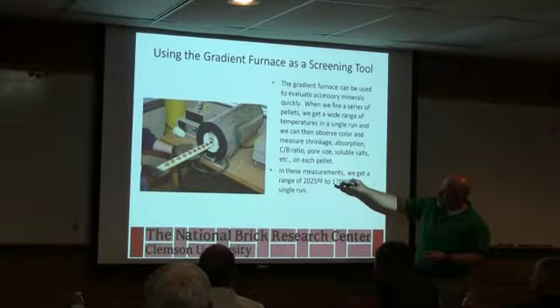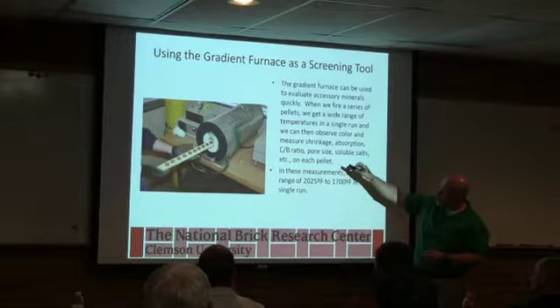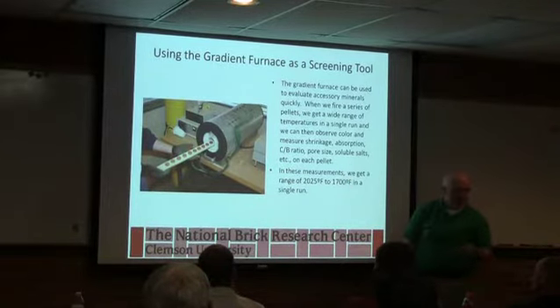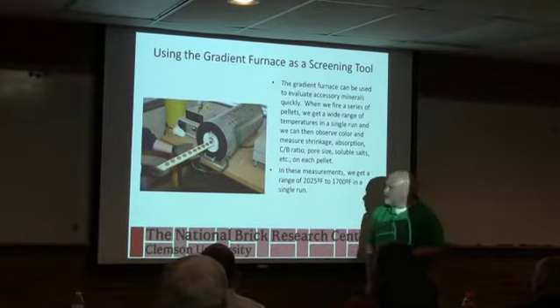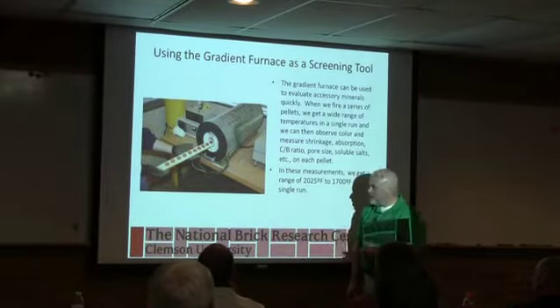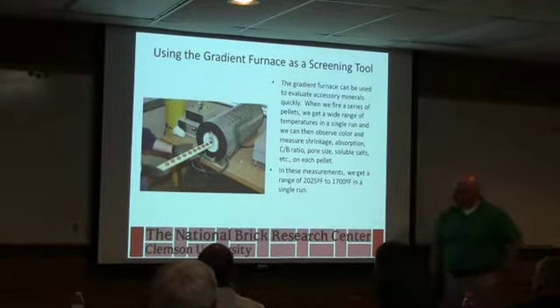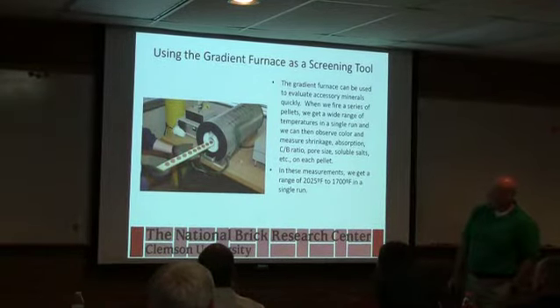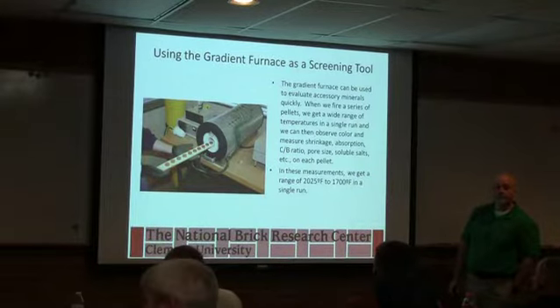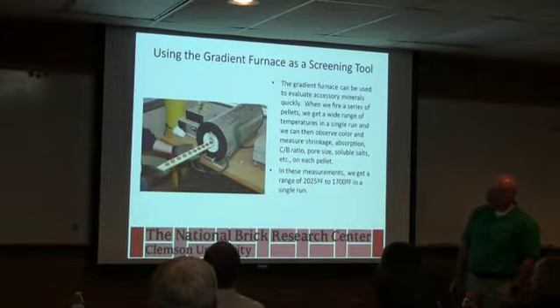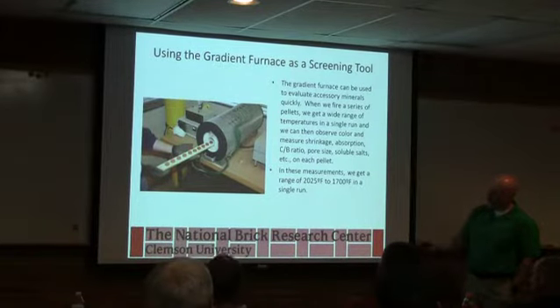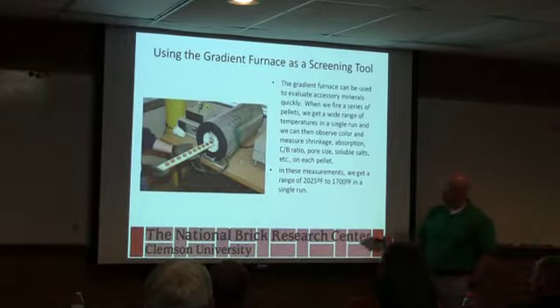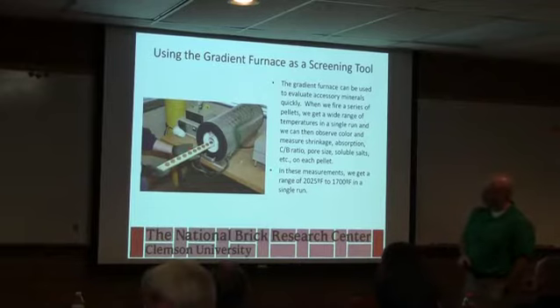Mike's got a way of recording the temperatures now, but if you do these little pellets and you make sure you line them up under the thermocouples, you can do water absorption on them and see how water absorption and color are influenced as a function of the firing temperature that the piece sees. So that's a good tool. Have you guys seen gradient bars? Y'all have. Most of the guys have seen a gradient bar. We don't use it nearly as much. If you go this pellet route, you can get a little extra information than just color and appearance.